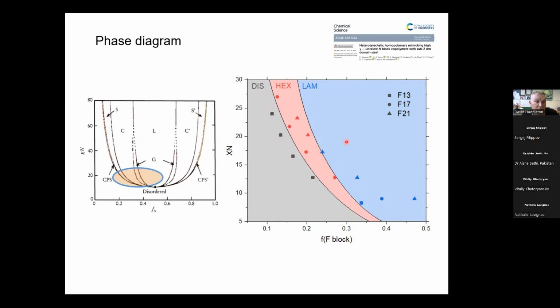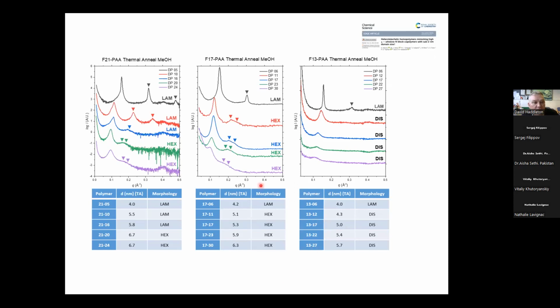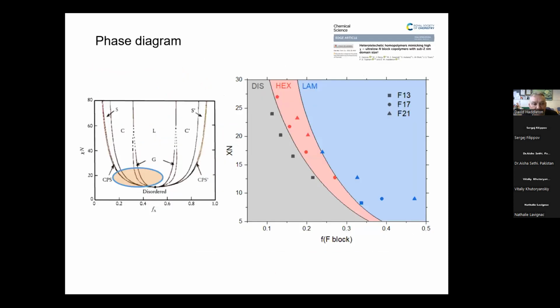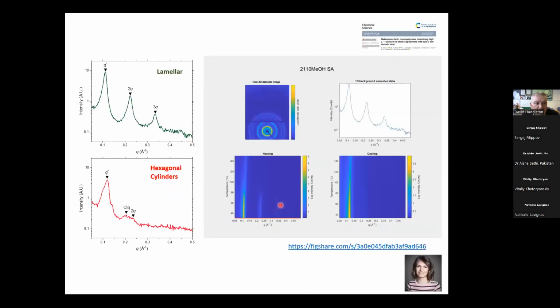And it just turns out that if we use the right ones, which is the smallest, it'll probably be the F21 with the smallest DP10, that probably will give us the smallest domain size. And I'm not going to show you the whole of this thing, but we will do SAXS, and we get these, and these 3 peaks show you it's a lamella, and something like this looks like it's hexagonal.